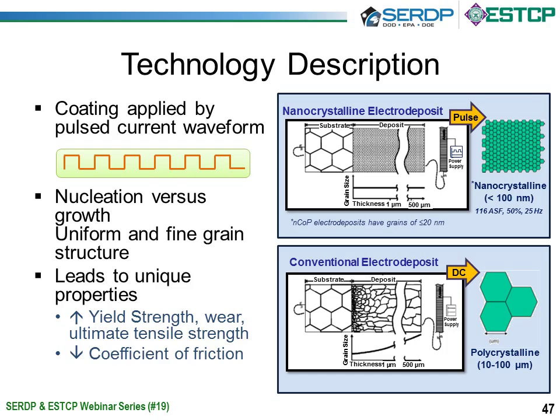So Ruben and I worked together with Integran and exploited that waveform that John was explaining earlier in his presentation. And we designed a specific pulse pattern that would allow us to have optimum properties for the cobalt phosphorus electroplate. So it does indeed produce a nanocrystalline structure. And as he mentioned in his presentation, that nanocrystalline structure modifies mechanical properties, which helps us compete better with the properties that chrome plating provides us for corrosion and wear.